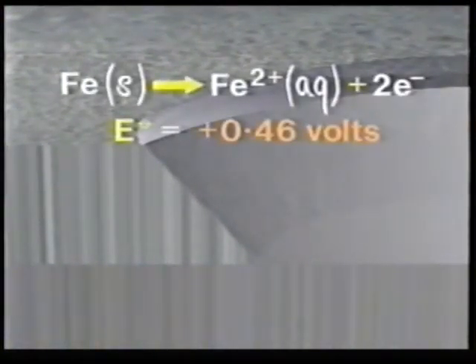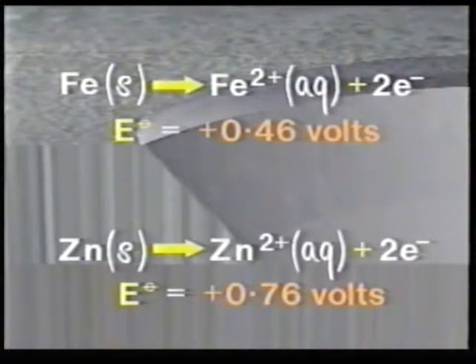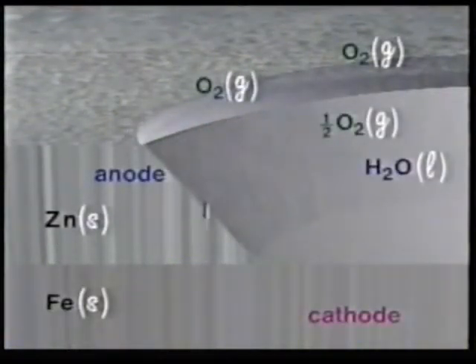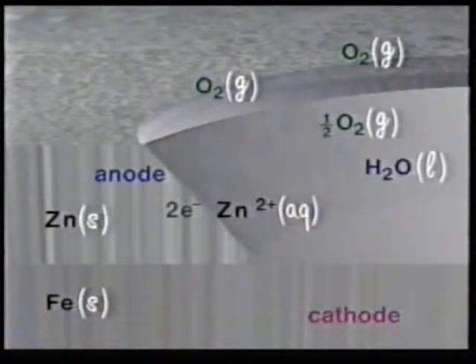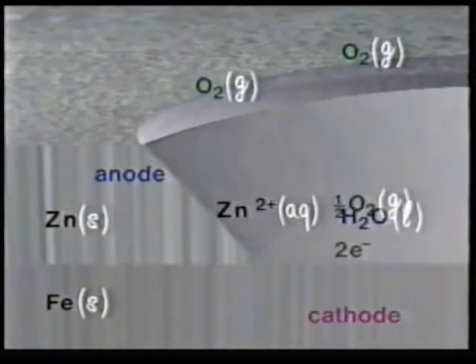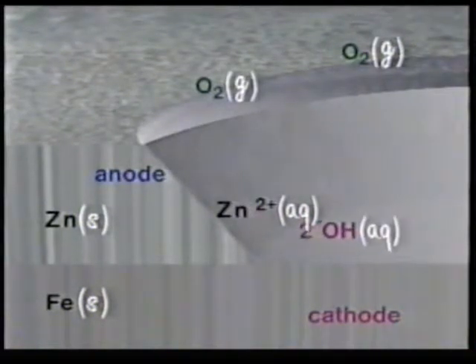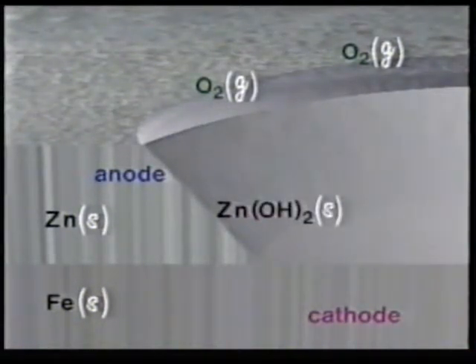With two metals present, there is the opportunity for one of two anodic reactions to take place, either this one or this one. Preferentially, the latter reaction will occur because the zinc is more electropositive than iron. So, zinc is sacrificed in the protection of iron, and in the anodic reaction it dissolves to form the divalent zinc cation. The cathodic reaction is the same as before, but this time it occurs predominantly on the exposed steel surface. The hydroxide ions produced combine with zinc ions to form zinc hydroxide on the zinc surface, and also to a limited extent on the exposed steel. This is an example of galvanic corrosion.